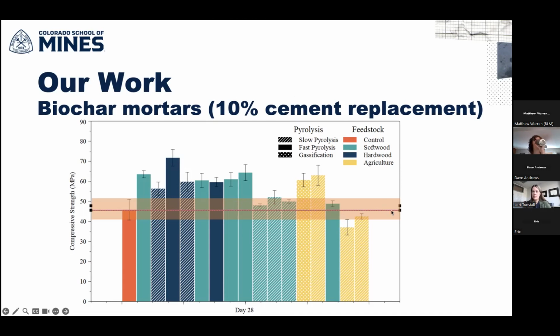This orange bar here is the range that we see for a control sample. And you can see here that the biochar mixes either mostly fall within the control sample, so a sample without biochar, or actually exceed it, with the exception of this one sample here to the right, which is an agricultural feedstock, and that performs a little bit worse. But out of the 16 biochars we've studied here, 15 of them behave similarly or better to a control. So like I said, that's great news in terms of application, but we were trying to understand that. We want to make sure that we understand our system so that we can control it and anticipate any adverse interactions.